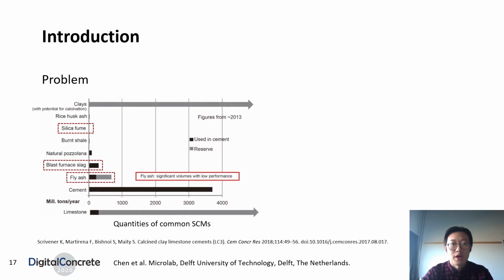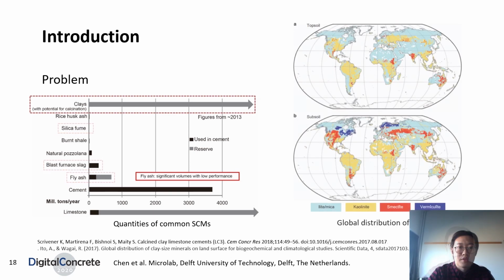Besides, common SCMs, for instance fly ash, slag, and silica fume, cannot be used for long-term development of sustainable concrete due to the limited stock and uneven distribution. However, clays, especially kaolinitic clay, which is the raw material of metakaolin, is widely available throughout the world, so calcined clay may be the best option of SCMs for developing sustainable cementitious materials.